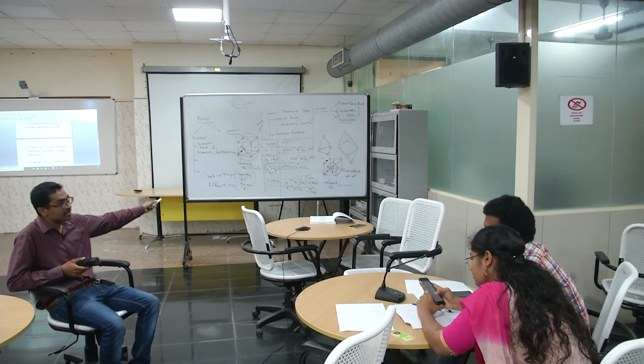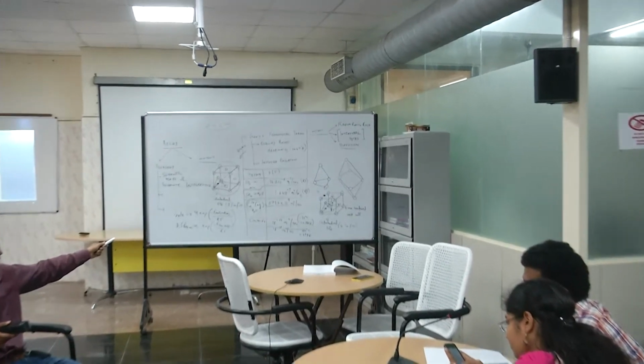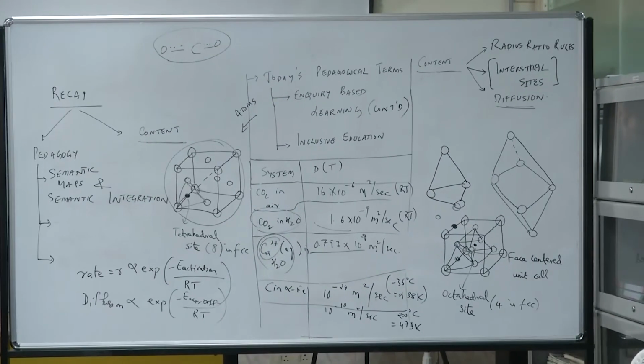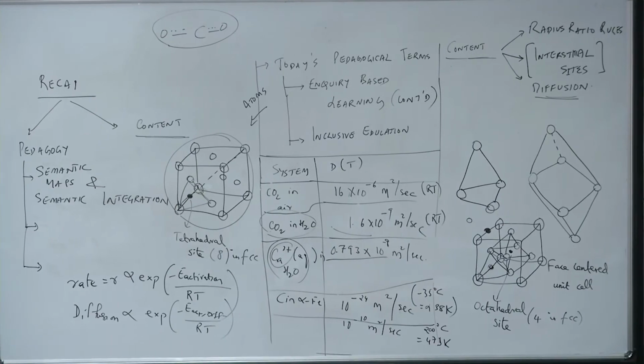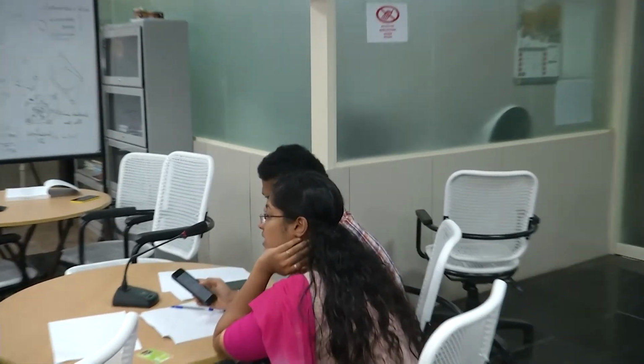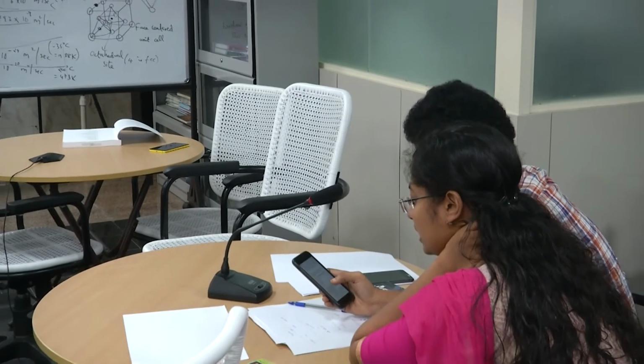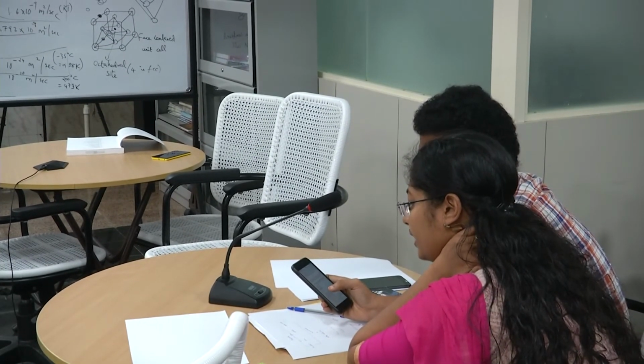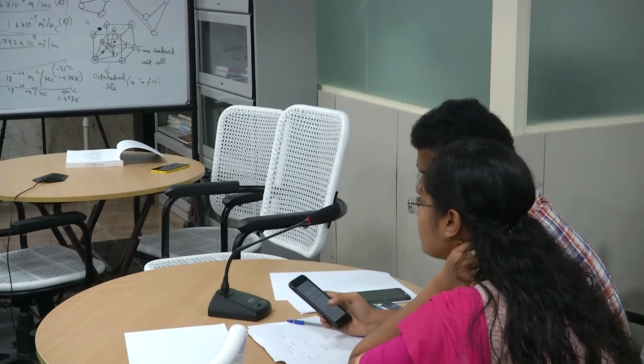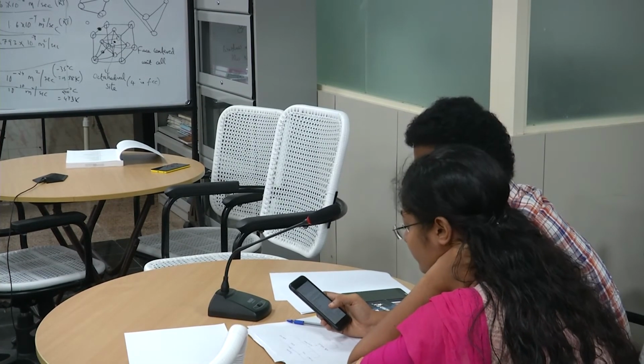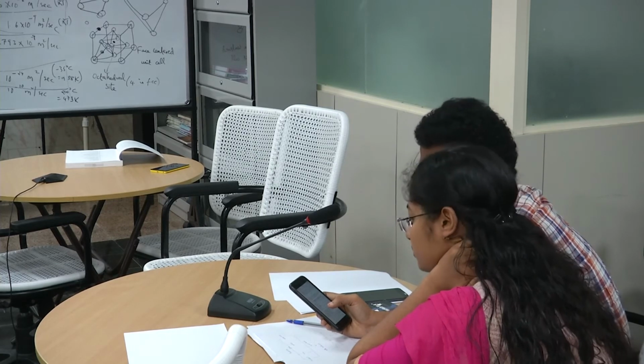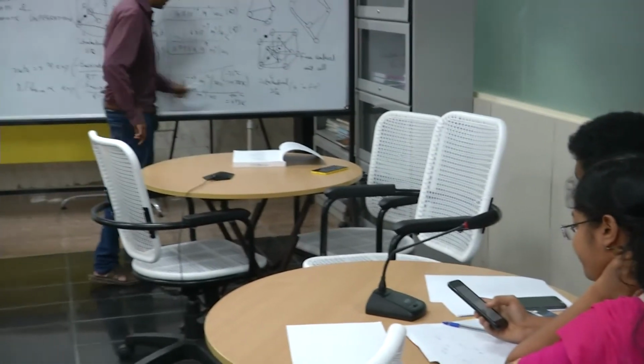Very temperature sensitive. But look at this. This is also very dramatic, isn't it? This is not a ceramic, and still you see 10 to the power of minus 24 meters square per second goes to 10 to the power of minus 10 meters square per second over 200 Kelvin essentially. Alright. What data did you find for polymers? Diffusion coefficient of oxygen in polyethylene at different temperatures. Yes, please tell me. At 263 Kelvin, it's around 0.8 times 10 to the power of minus 10 meters square per second. So that is comparable to this, isn't it?